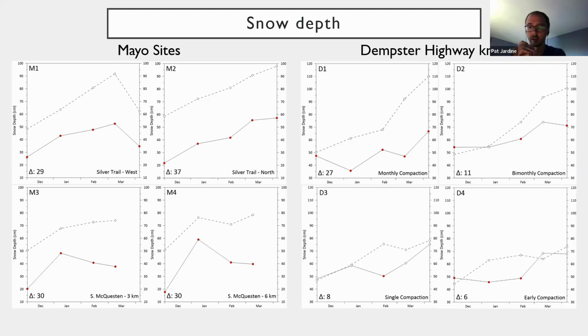But all the other sites were mostly pretty fine as expected. Because the Dempster sites were in tundra, the snow was hard enough to walk on, and measurements were taken from the center of the plots. At the Mayo sites, the snow was too soft, so measurements were taken by leaning over the edge from the embankment to minimize disturbance. At the Dempster Highway, both sets of plots began at about 50 centimeters snow depth, but the compacted plots only rose to about 70 centimeters over the course of the winter, while the undisturbed plots rose to about 80 to 100 centimeters.